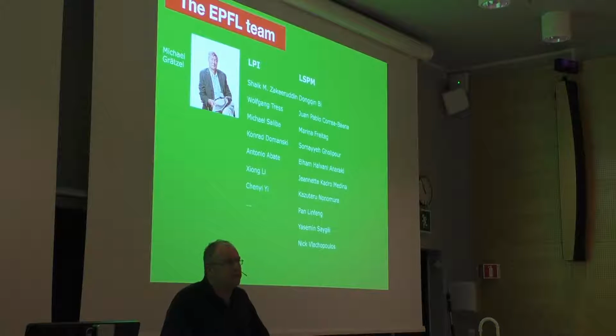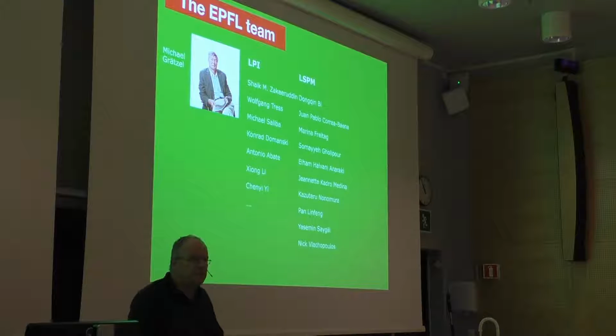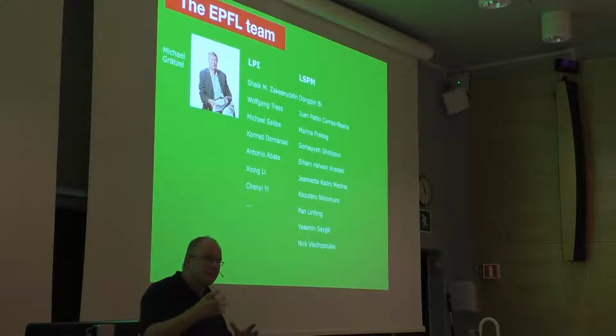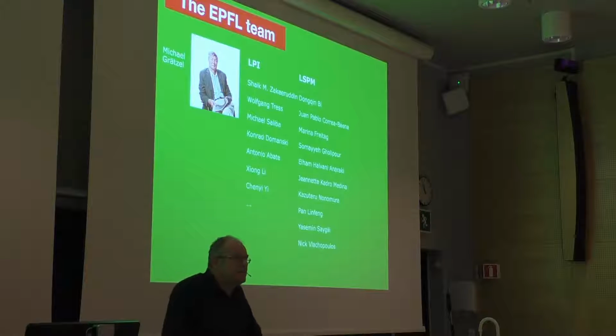People have tried all kinds of things. The other one which I think can be interesting is bismuth, where at least people see a nice perovskite structure formed, and there's also a group at Stanford doing bismuth silver as a combination. So if you have to replace the 2+ lead, you take one 3+ and one 1+, and see if you can combine. Still not so high efficiencies there, but that's interesting. It's important work to do, but so far very, very challenging, I would say.